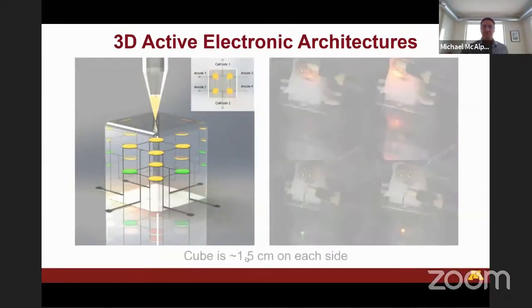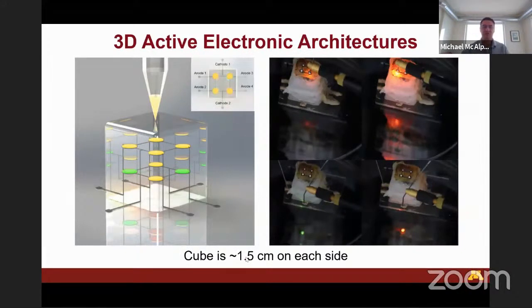And we can build electronics into 3 dimensions. This is a cube where we basically incorporated 8 multicolored LEDs built up into 3-dimensional space in this cube. Again, this is an example of the multi-scale because now we have nanoparticles as the active layer, we have microscale printing, and we have a macroscale device, this cube made of silicone, 1.5 centimeters on each side, where if you probe the different electrodes on the cube, you can see it lights up the LEDs within the cube. Entire structure 3D printed: the silicone, the liquid metal, the quantum dots, the silver nanoparticles. All these materials normally thought of as distinct, all coming together on a single platform to print this electronic cube.